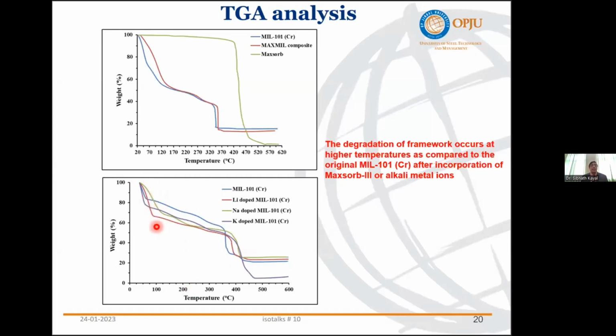Then you can see from 100 to around 350 degrees centigrade, there is a slow reduction or slow weight loss. This slow weight loss is due to whatever polymer materials or any other gases are present inside the MOF structure, and so the degradation, not the complete degradation, but the degradation of the polymer chains.